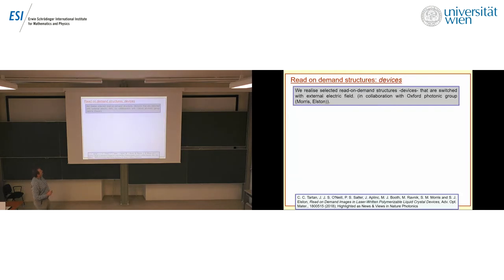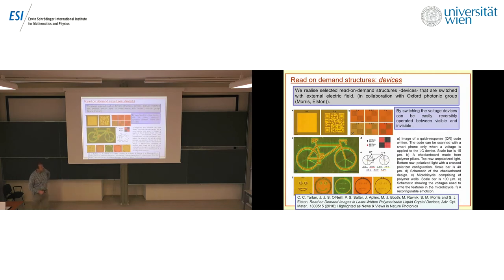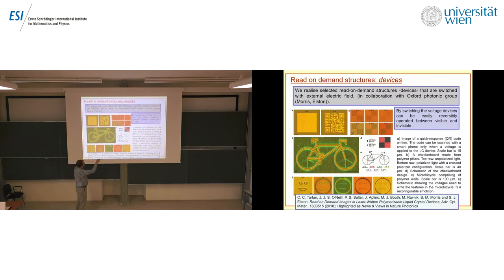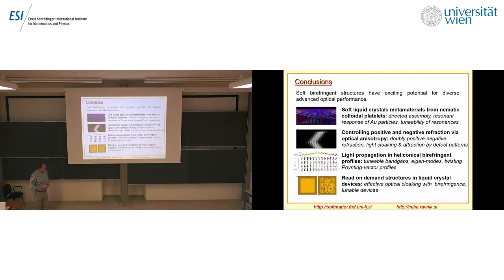Knowing how to do it for one pillar, you can create an array of pillars where each column is written at a different voltage. When you read at zero volts, the first line of pillars is invisible. As you move the read voltage, you control which objects become visible. When the read voltage equals the write voltage, you have the largest contrast and see those objects — essentially cloaking. They demonstrate this with a QR code where pillars were written at different voltages, so at five volts some pillars are visible and some are not, allowing active tuning of what you see. They also draw a bicycle image to show control of intensity in different spokes, and design smiley faces — all by just changing the voltage on smartly designed pillar objects.